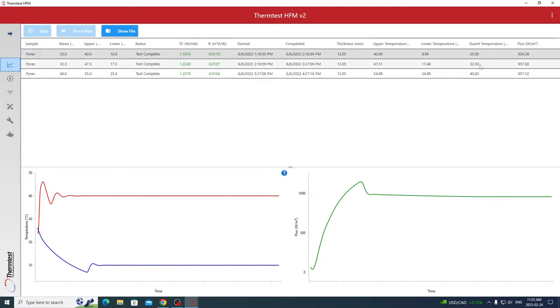Now, in an isotropic homogeneous sample like Pyrex, we could measure it by all of these methods, transient and steady state, and we get a pretty good value. It's when you introduce complex materials that are, again, heterogeneous, non-repeating layering through the thickness, or complex materials. So this gives you a high confidence through-thickness heat flow, or one-dimensional thermal resistance and thermal conductivity.